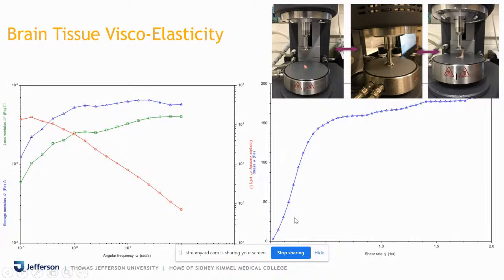And we were also able to see from the stress versus shear rate curve that the viscoelastic behavior of the brain is pseudoplastic in nature, which is common with most hydrogel systems. Now, in our experience, most natural materials like polysaccharides such as chitosan, carrageenan, alginates, and hyaluronic acid, all these biomaterials have a tendency to form physically cross-linked hydrogel systems.